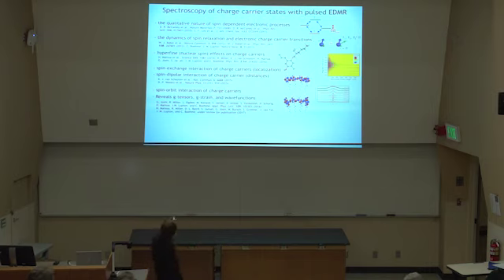We can learn something about the quantitative nature of the spin coupling in these systems. I showed hyperfine coupling effects, meaning nuclear spin effects. I showed how to measure spin exchange by analyzing your Rabi wiggles, your Rabi frequency shifts, and spin dipolar interaction, which tells you something about distances. And then if you look at spin-orbit interactions, it gets complicated. But in combination with simulation, with theoretical data, you can also obtain some fairly unambiguous insights into the nature of your systems.